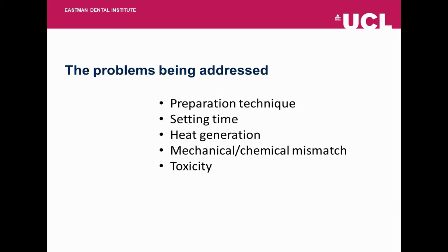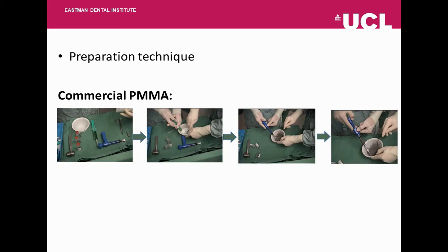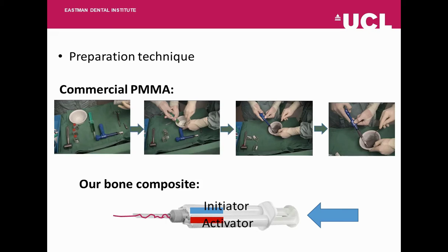So the problems I'm addressing in my PhD are the preparation technique, setting time, heat generation, mechanical and chemical mismatch, and toxicity. Looking at the preparation technique, most commonly commercial polymethylmethacrylate cements require a bit of equipment. You get a powder form, which then needs to be mixed into a liquid form, and then is taken up using a syringe and then applied to the patient using an injectable syringe. Our composite doesn't require any of these steps. Our composite can be directly applied to the fractured site using a double-barrel syringe, where the double-barrel syringe consists of two separate components. They're pressed at the same time, pressure is applied, and they're both mixed via the automatic mixing tip, and our paste is ready to start the reaction, which I will discuss further in the presentation.